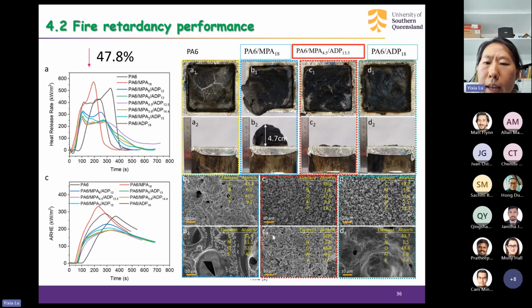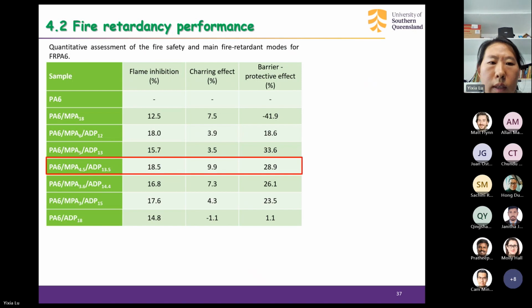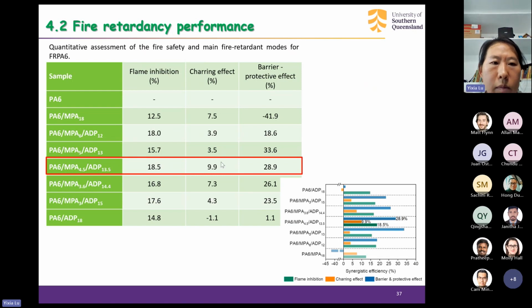We also investigated the char layer. As we can see here, pure PA6 burns out after combustion. But for MPA and ADP addition composites, there are visible char layers here. And we also use SEM to explore the internal layer. Similar to the previous work, this formula of composite performs best with a high flame inhibition, charring effect, and barrier and protective effect.